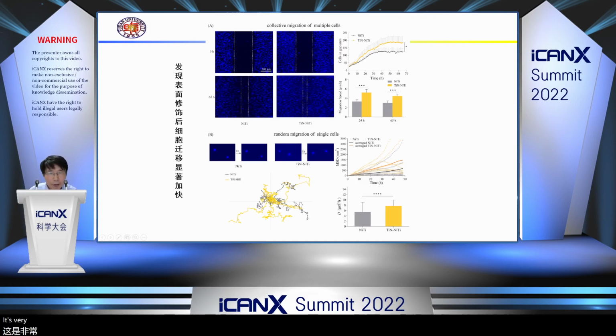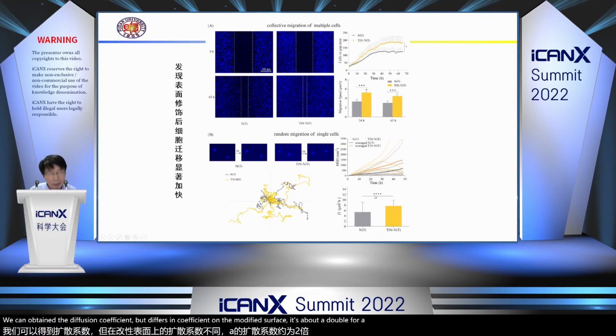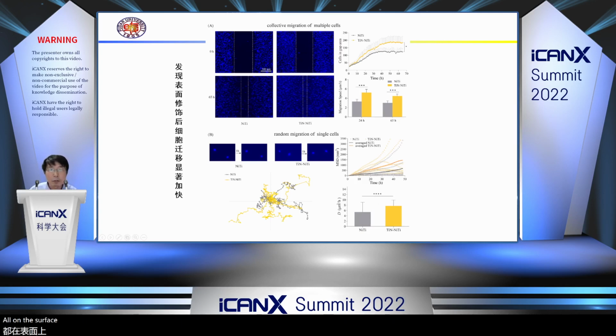It is very interesting that the random migration obeys the Brownian motion equation established by Albert Einstein in one of his famous papers in 1905. Now, the mean squared distance exhibits a linear function of time. In this way, we can obtain the diffusion coefficient. The diffusion coefficient on the modified surface is about double that on the surface without coating.